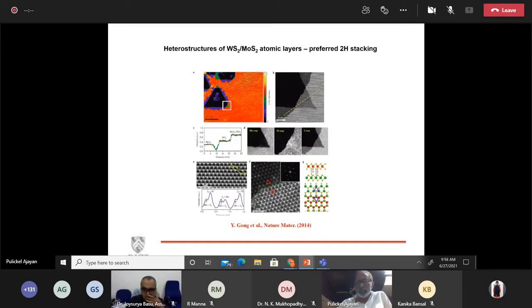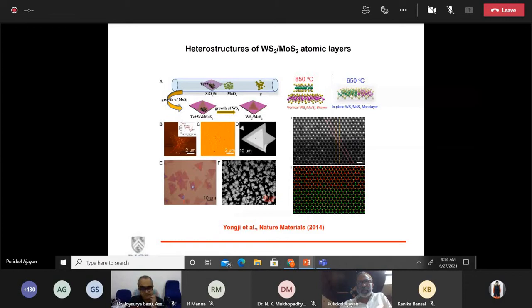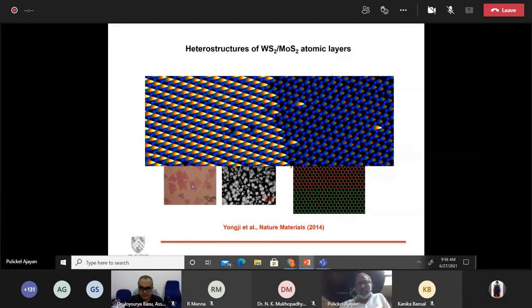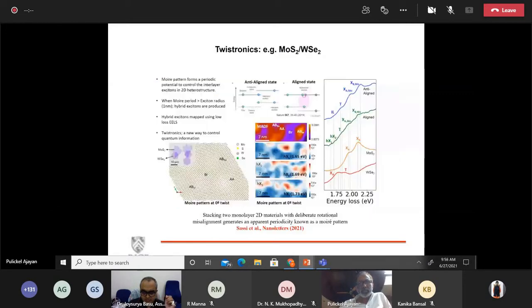And again, I don't want to go into details of these characterization methods and all that, but we have found windows of growth process where you can create these preferentially 2H stacked materials. Again, that depends on the way these metal atoms sit on top of each other from different layers. Or we can preferentially create materials that have this in-plane structure. And when you say in-plane, these are really very interesting interfaces because they are almost atomically flat interfaces between the tungsten sulfide and molybdenum sulfide. And of course, you can see some atoms that are diffusing into the neighboring domain. But one could essentially think of creating really sharp interfaces in all-2D hybrid material structures.